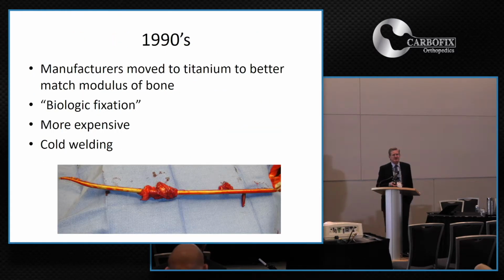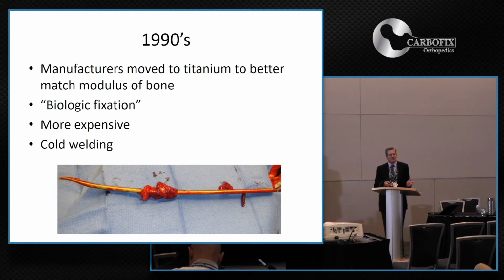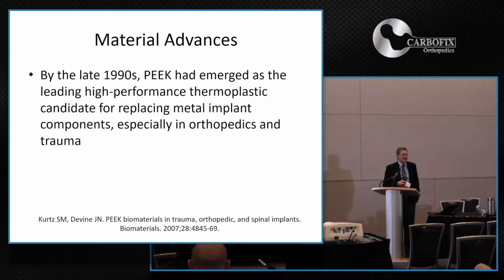Well, in the 1990s, manufacturers changed many of them to titanium for its better match to the modulus of elasticity of bone. Discussed this biologic fixation with titanium. It was also more expensive, and there were problems of cold welding when we tried to remove these implants. And by the late 1990s, PEEK had emerged as the leading high-performance thermoplastic candidate to replace metal.